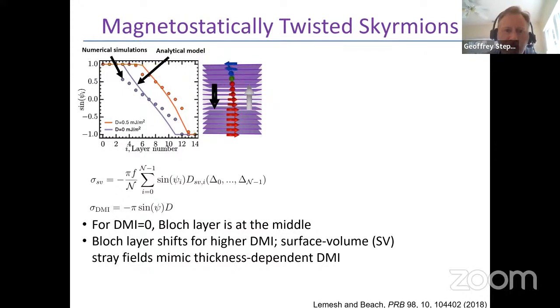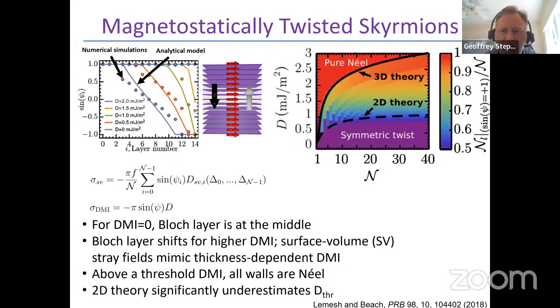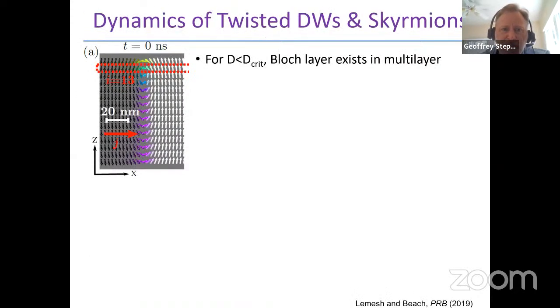So the green arrow shown here is very, very non-stiff. That is to say, the energy that wants it to be Bloch and the energy that wants it to be Néel are almost completely balanced. So the energy or the torque that's required to cause that layer to precess is very, very low. And that precession is exactly what limits the high-speed dynamics. So not only is there a very large DMI required to have the structure fully Néel statically, but the stiffness of the domain wall, which protects it against precession during translation, and precession of a domain wall or any texture during translation is something that's known as Walker breakdown.